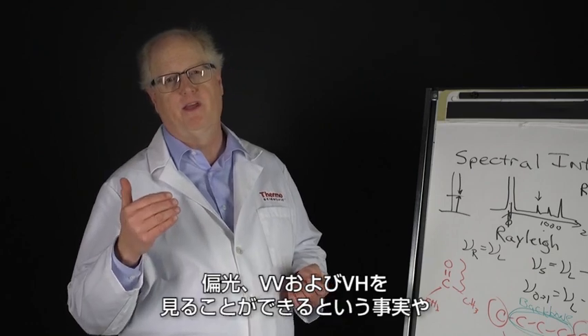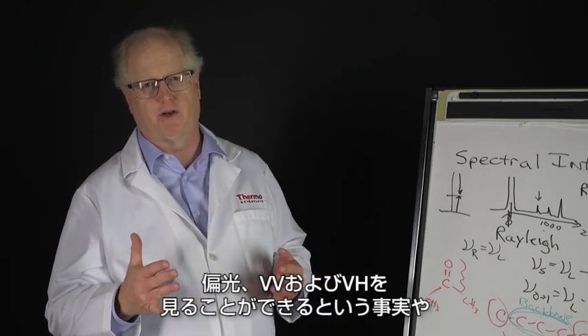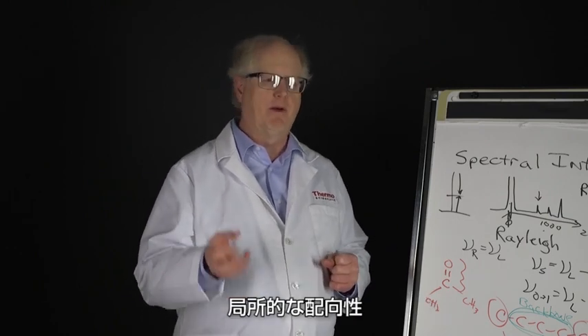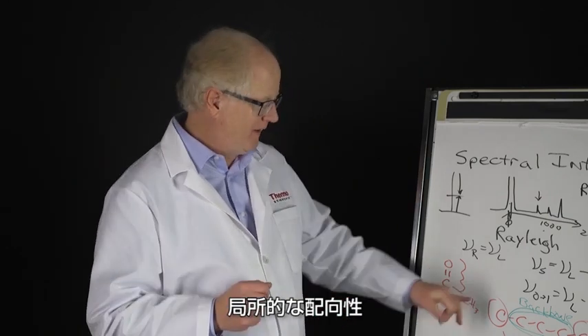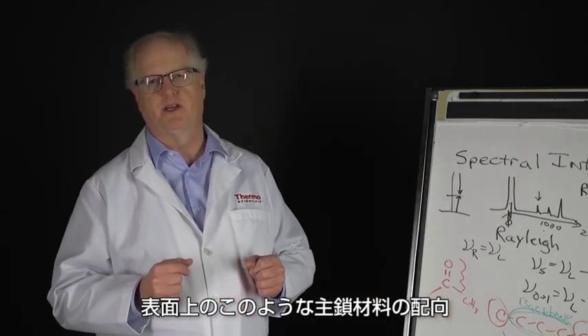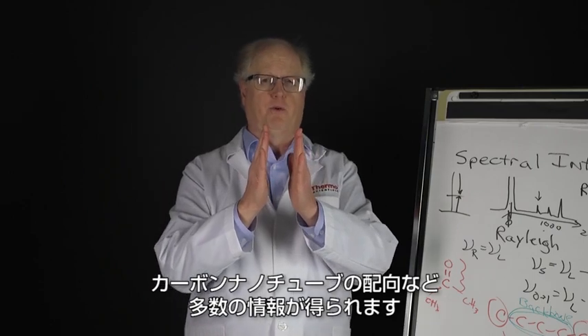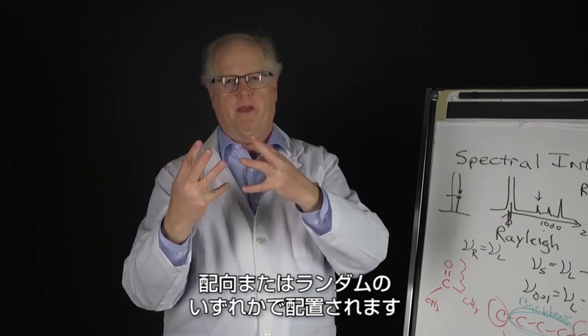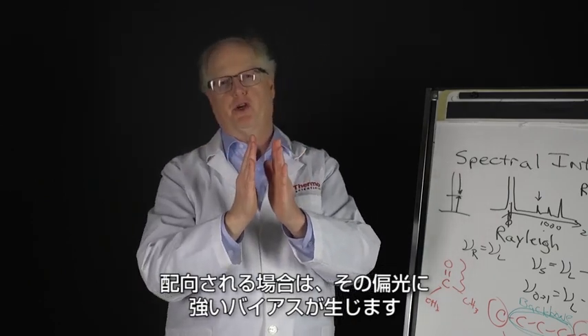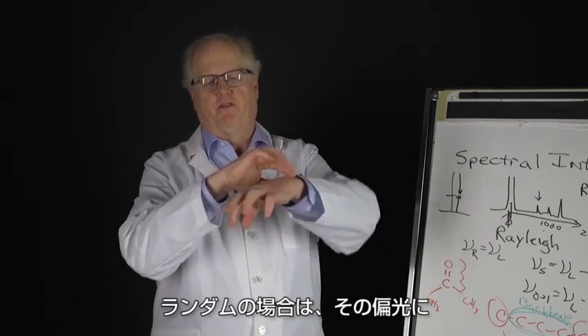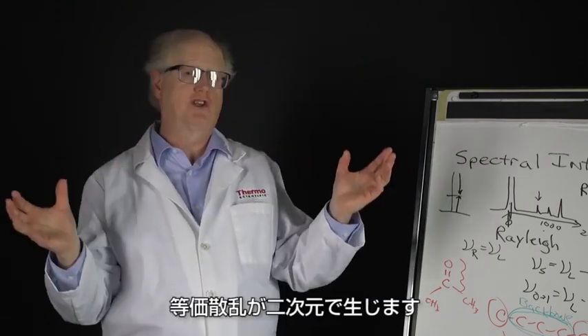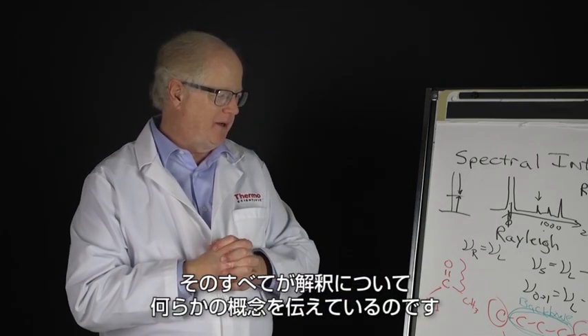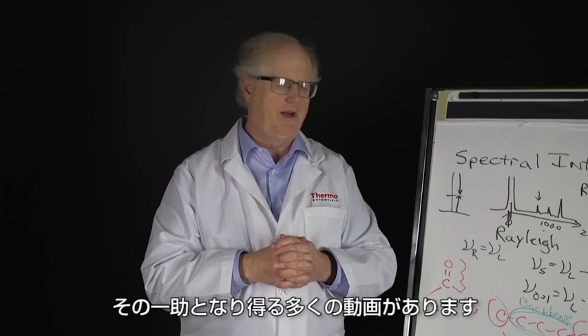So Raman and infrared both give you a lot of data, but Raman gives you a little bit more, including with the polarization - the fact that you can see the VV and the VH, the difference between those two - and they can tell you a lot about the symmetry, about the alignment, the local environment, the alignment of a backbone material such as this on a surface, the alignment of carbon nanotubes. As the carbon nanotubes are laid down on a surface, they can either be aligned or random. If they're aligned, then the polarization shows a strong bias. If they're random, then the polarization shows essentially the equivalent scattering in the two dimensions.